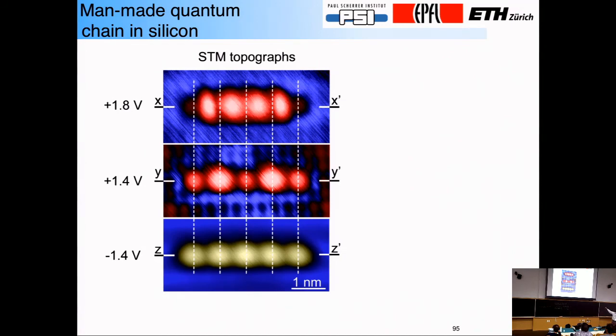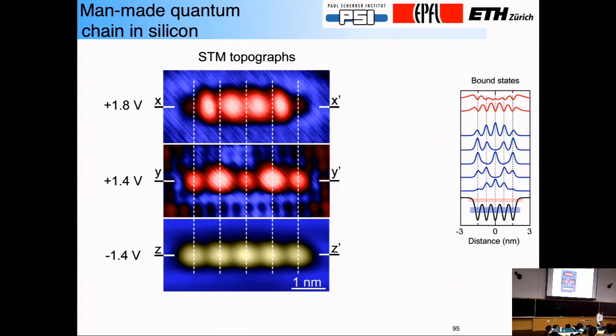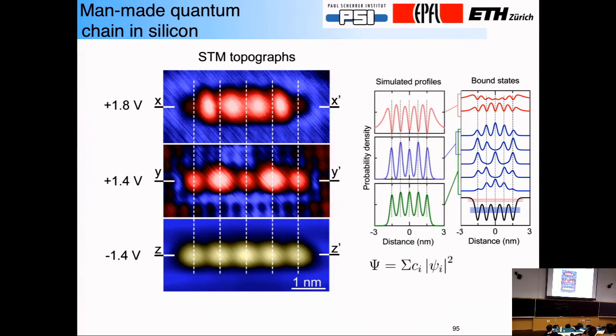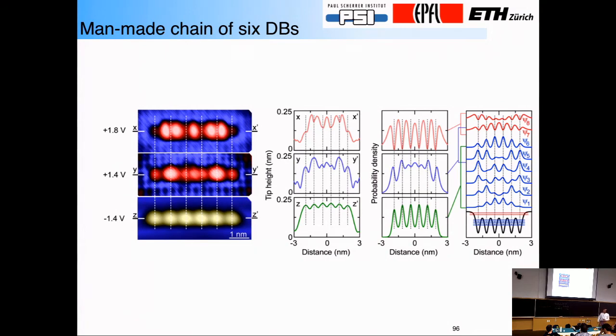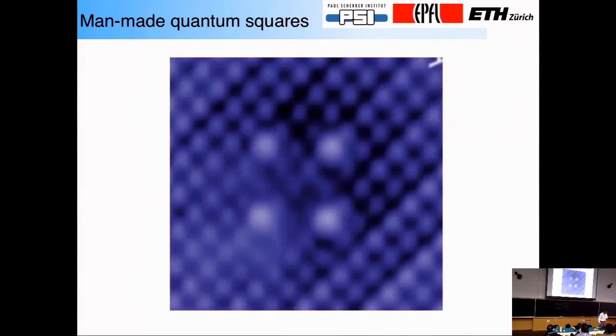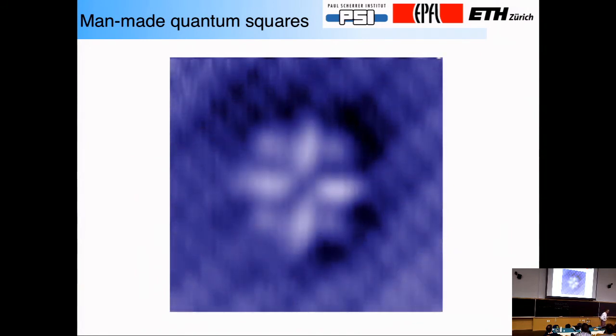On the other hand, if I change the bias voltage, then I occupy a different state, a state which is only between these atoms. So I have a model quantum well system that I can build on the surface of silicon. And I can not only build it, but I can control it with STM and measure its properties. Here are some calculations that we did to account for these densities. I could do it with 6 atoms, I could do all kinds of things. I can even make squares. And by changing the tip sample voltage, I can get different wave functions to pop up. Here the wave functions are centered on the vertices of the square. If I change the voltage, I get a flower. So I have control over orbitals in essentially the world's most common material at the surface.